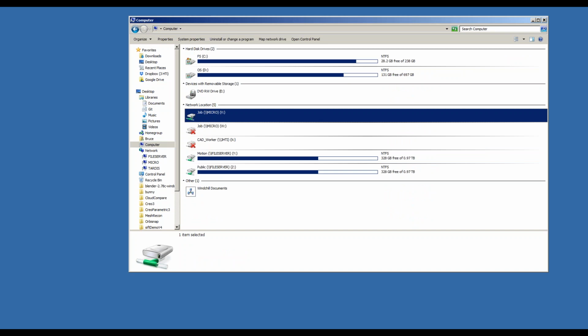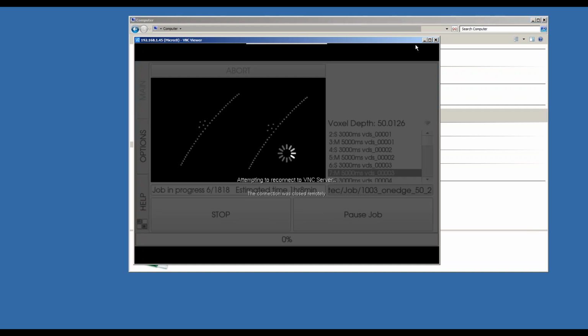Once the print is done, you take the job off the build table. Because it is UV curable, you first wash the part in isopropyl alcohol. Once you wash it, it then goes into a curing station to fully cure the part. Coming off the printer, the material is only cured to about 70 to 80% of what it needs to be cured to. So putting it into the light box when you're all done finishes curing. And now I lost the connection to the machine. All right, why don't we just open up the floor for questions, Rob?